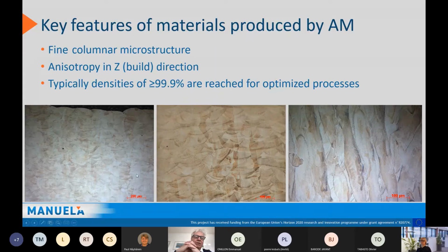But it's also important to understand, at least in laser powder bed fusion, that it's a rapid solidification, rapid cooling technology. So the material will locally always undergo a cooling rate on the order of 10^4, 10^5, 10^6 Kelvin per second. That is what's happening. So of course, it's material that is built locally with very, very high cooling rates. That is inherent in the technology itself. Next slide.